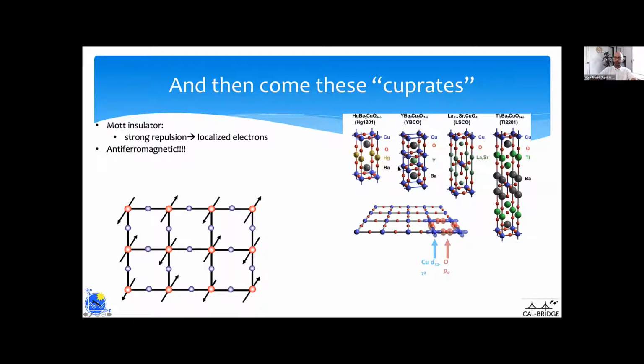And these are the different kinds of chemical ways to achieve this compound. These different chemical formulas, but I just want to show you that it turns out that all of them have in common a planar molecule, if you will, of copper and oxygen like this, and they're bonded like in these orbitals like that. And it turns out that the coppers, indicated by these little arrows, like I said, are antiferromagnetic. So in theory, these should be very, very not superconducting.